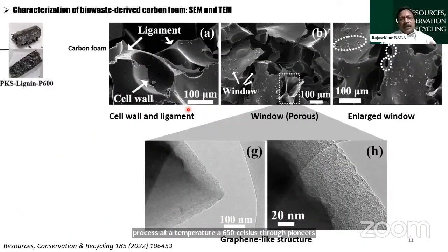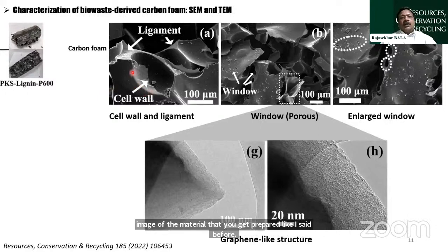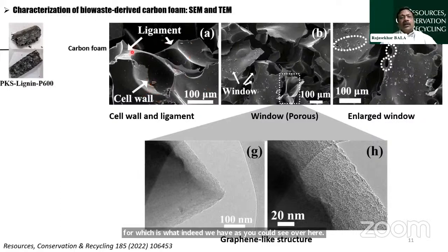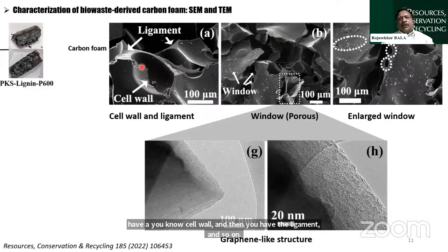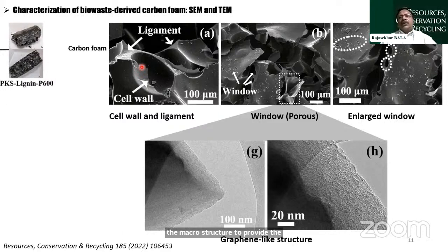Okay, so this is an image of the material that we have prepared. Like I said before, what we are looking for is the closed-cell carbon foam, which is indeed what we have. As you could see over here, we have a cell wall and then the ligament, and so on. The cell wall and ligament integrate the macrostructure to provide the rigidity of our carbon foam. That's one of the important requirements we have. At the same time, the windows here represent the tiny little pores we have in the material. That's important for the CO2 gas to diffuse from the gas phase into the interface over here, and that will be locked in. This is how the adsorption process would occur.